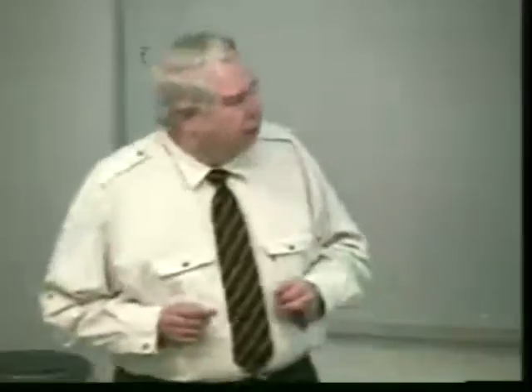And we show this for various reactor coolants. Here we show it for water. It takes about 3/4 of a pipe. For sodium, you need 2 pipes. For helium, you need 12.5 pipes. For molten salt, you need a half pipe. Now this is very important because the size of your pumps, the valves, the piping, the major components in a reactor are dependent upon the ability to transport heat. The better the fluid is at transporting the heat, the smaller the equipment, and hence there's a strong incentive to have the right properties of the coolant.